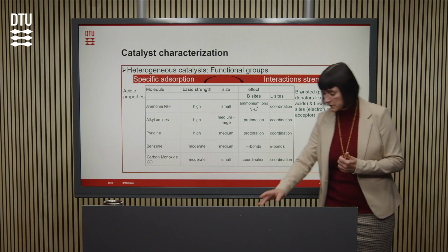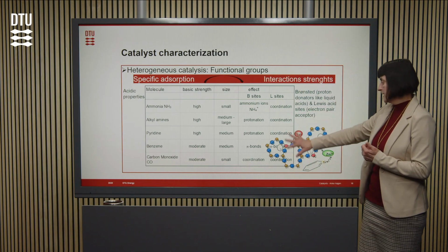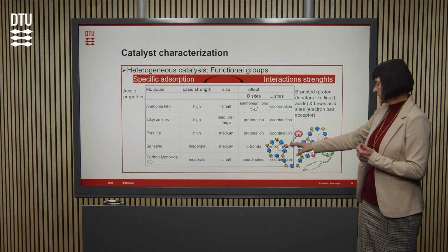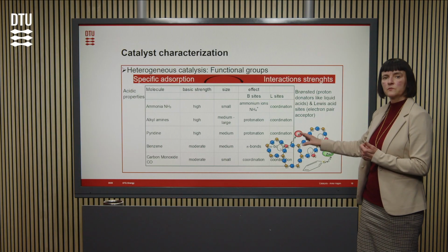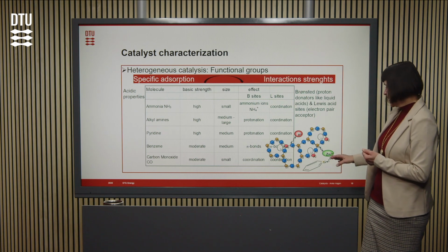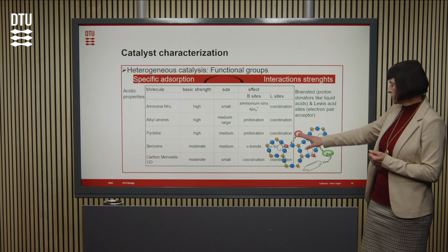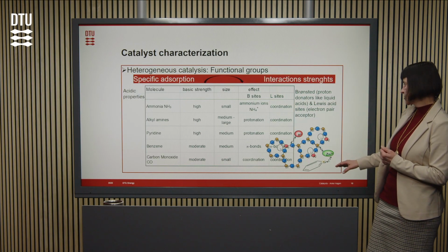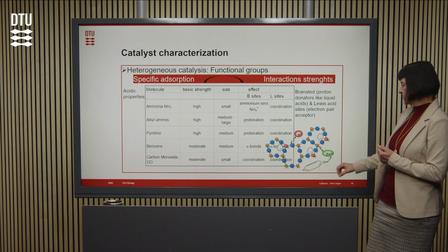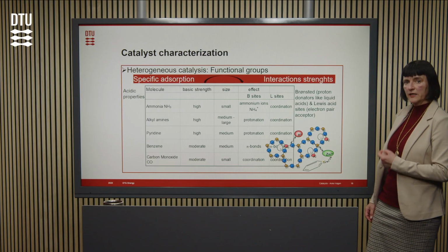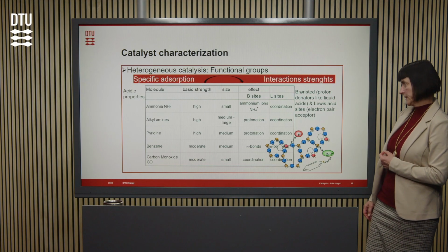And I have a short illustration, this is illustrating a zeolite. If you have a functional group, an OH group, that would be this one, illustrating a Bronsted acid site. So this proton is easy to donate to a reactant. And in addition, if I have, instead of a proton, a zinc ion at the same position, that actually has an electron pair that could interact with another basic molecule. So these are the two types of acid sites that we are looking at right now.